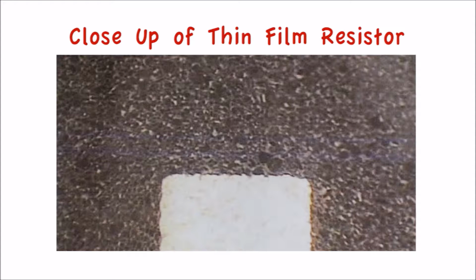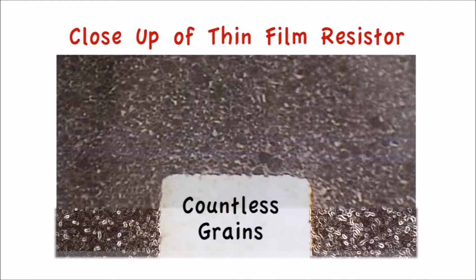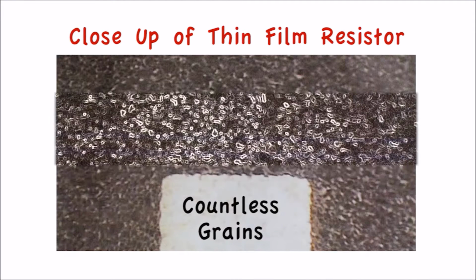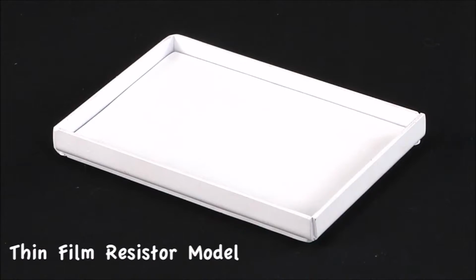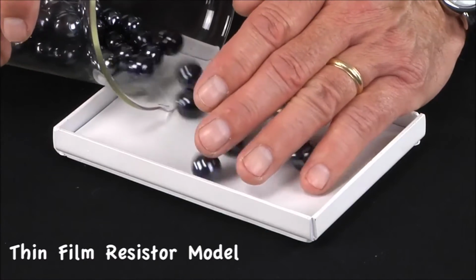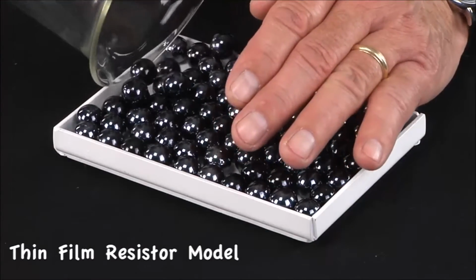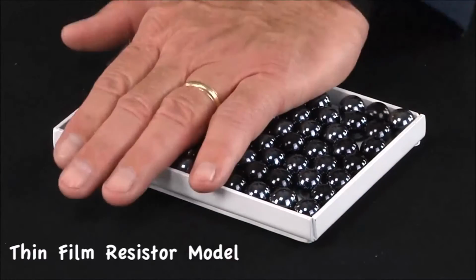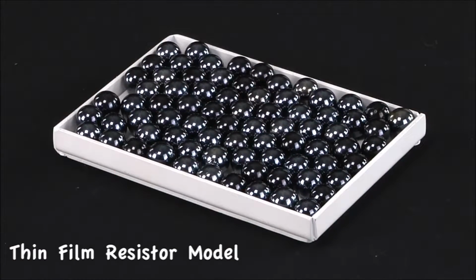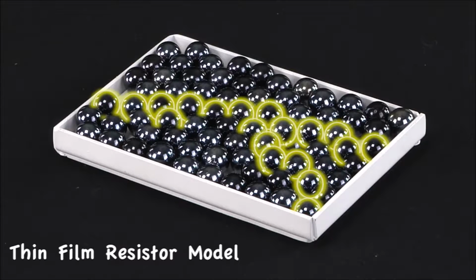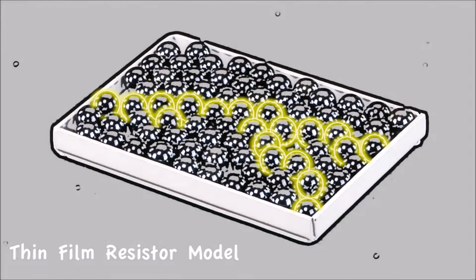Here's a high magnification close-up of the element of a thin film resistor. Note the surface. It's composed of countless grains of conductive material. Let's look at an example that makes it a little easier to envision this structure by packing some marbles into a tray. The marbles represent the conductive grains we saw in the high magnification photo. Note the countless resistive interconnects and current paths between the conductive particles. This is a good model of a thin film resistor.